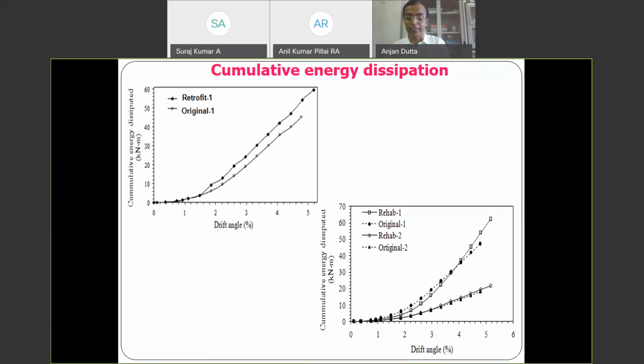So thereby, your rehabilitated specimens are as good as the original. And mind you, the damaged specimens which we tested initially, before the rehabilitation, were tested to a load level so that the degradation in load carrying capacity was as high as 40 to 45%. Now you imagine a structural element which has been degraded by 45%. Now we have rehabilitated them using epoxy injection, and you can see that the capacity is back to the original capacity. So even for a damaged specimen which is as degraded as 40 to 45% capacity, it can be brought back to the original load carrying capacity. So that's a very encouraging sign actually.